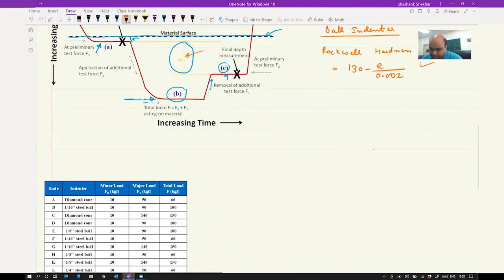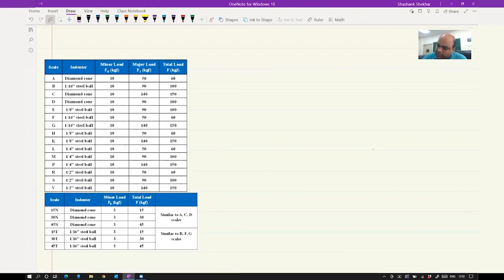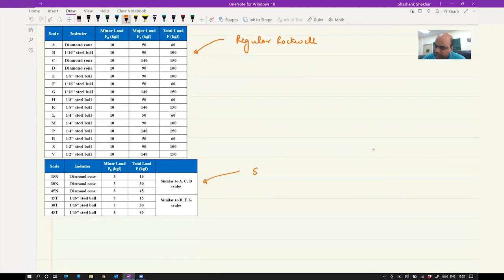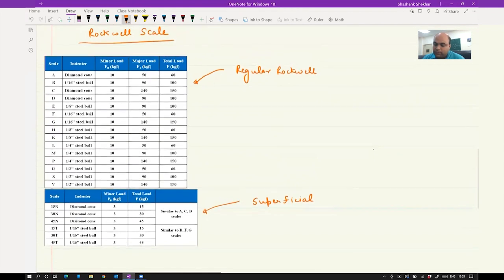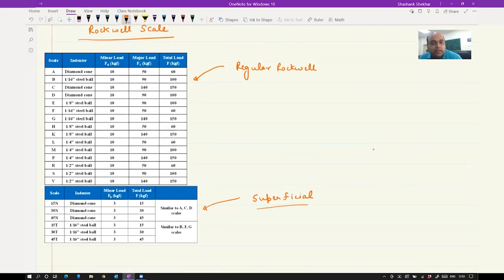Here I'm showing you a table. This is for regular Rockwell, which is your Rockwell scale overall, and this is for superficial. There are two types of Rockwell scale: one is the regular Rockwell scale, another is the superficial Rockwell scale. In the regular Rockwell scale, you will see the load value is high. Here I have mentioned in this column the type of indenter, and this is the scale. As I mentioned before, B and C are the most famous ones. When we use the B scale, if you remember the dial I showed you before, there we had the B scale and the C scale.